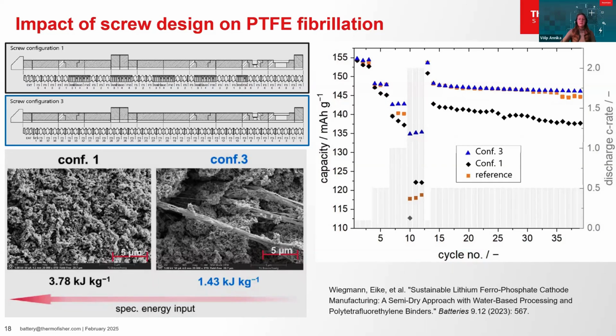The left SEM image shows the cathode mixed with 5 kneading blocks. The PTFE fibrils are small and well distributed. The right SEM image shows the cathode mixed without kneading blocks. The PTFE fibrils are much larger because the mixing here relies only on particle-particle interactions, and the lower energy input is insufficient to evenly disperse the PTFE.